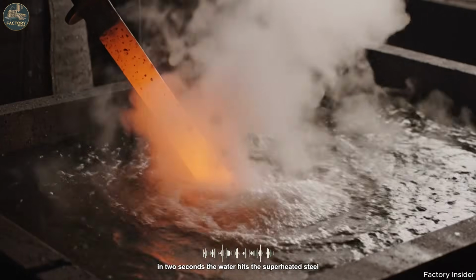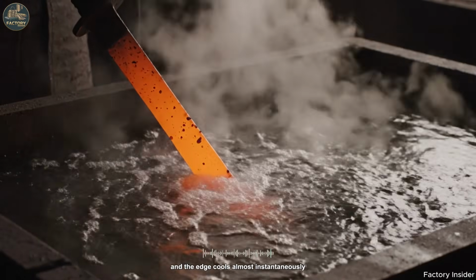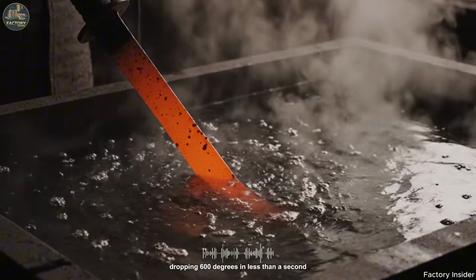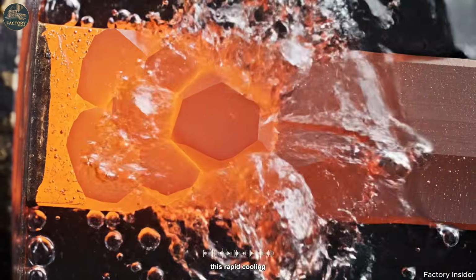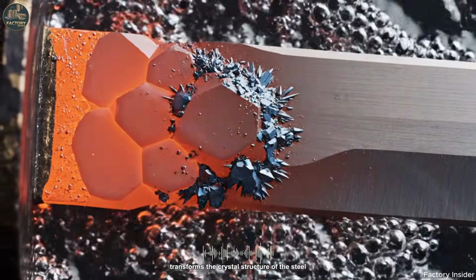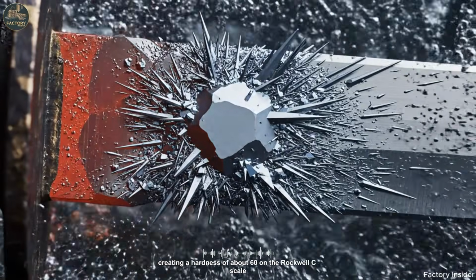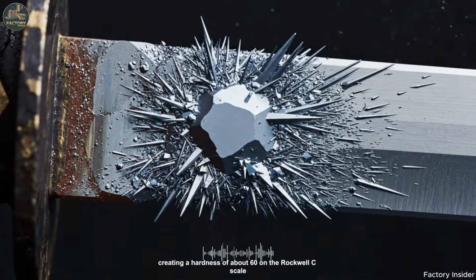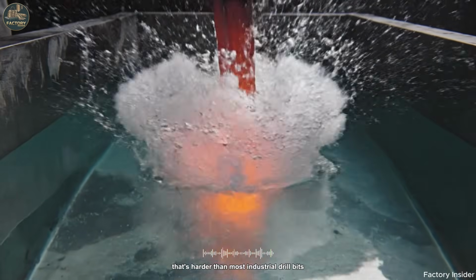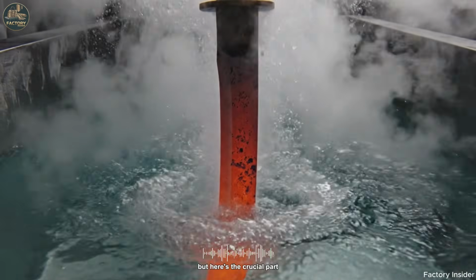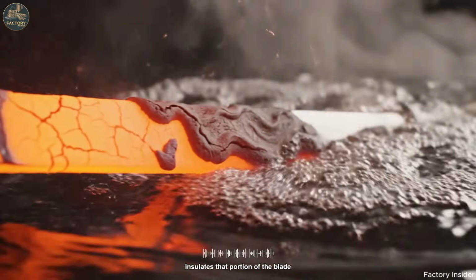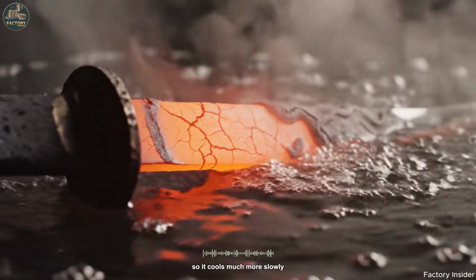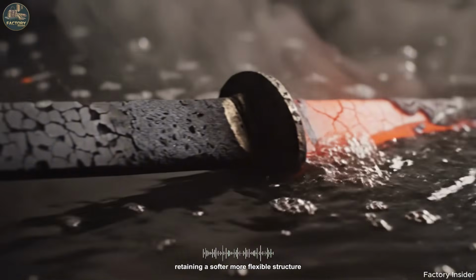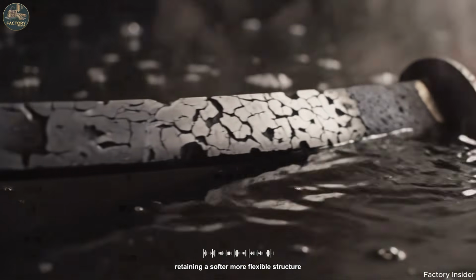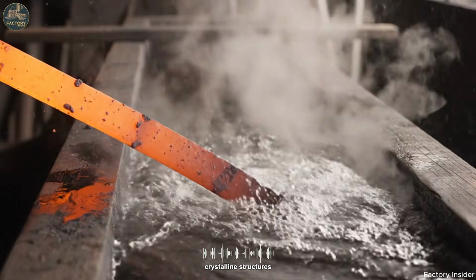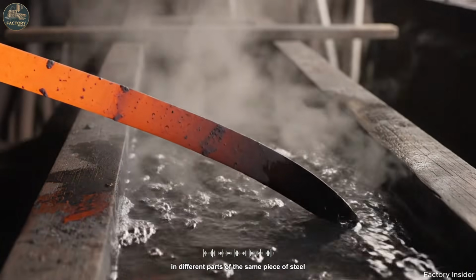The water hits the superheated steel and the edge cools almost instantaneously, dropping 600 degrees in less than a second. This rapid cooling transforms the crystal structure of the steel from austenite to martensite, creating a hardness of about 60 on the Rockwell C scale. That's harder than most industrial drill bits. But here's the crucial part. The thick clay on the spine insulates that portion of the blade, so it cools much more slowly, retaining a softer, more flexible structure. The differential hardening creates different crystalline structures in different parts of the same piece of steel.